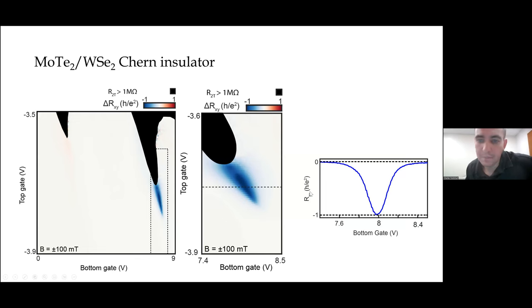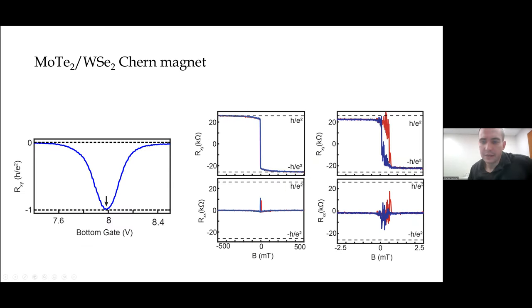So I'm going to zoom in on that regime. And indeed, you can see realization of a quantized anomalous Hall effect here. I've shown a line cut through here so that you can see us reaching quantization of the anomalous Hall resistance in more detail. And we can park the electron density and displacement field right in that regime and do a magnetic hysteresis loop. So you can see that at a couple of hundred millitesla, we realize a quantized anomalous Hall resistance. And at very, very low field, we have a magnetic hysteresis loop, although we don't see quantization at zero field.